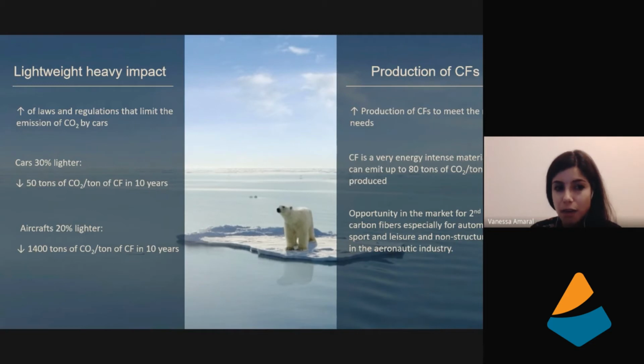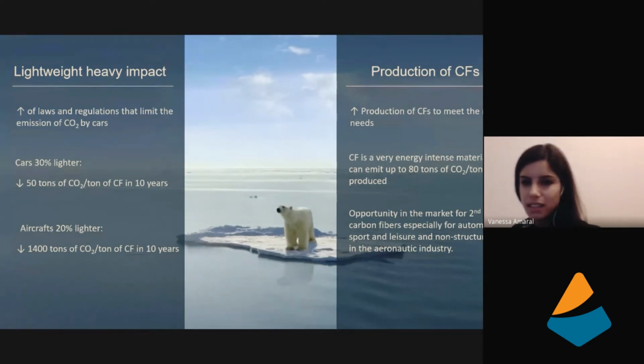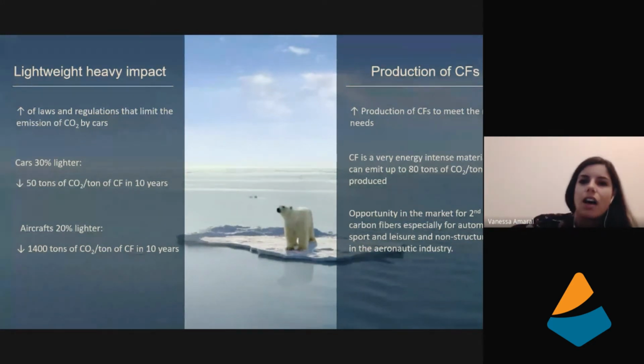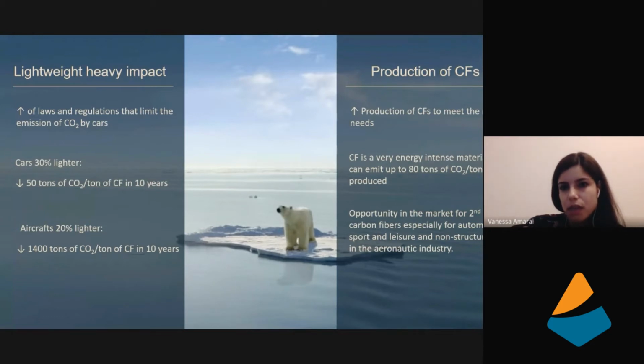If you consider aircraft, if they are 20% lighter, you're going to have a reduction of 1,400 tons of carbon per ton of carbon fiber in 10 years. So it's a huge decrease in emissions, and it's very interesting to lighten transports. However, the production of carbon fibers is a very energy-intensive process that can emit up to 80 tons of carbon per ton of carbon fiber produced, which is huge.